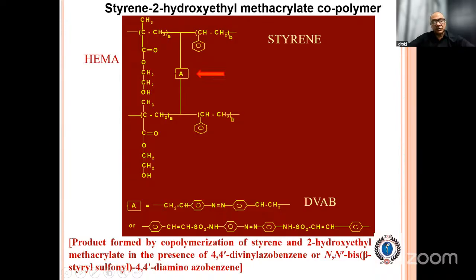So this polymer will be exclusively used for delivering drug to the colon because it is degraded only in the colon. This azo bond will be cleaved in the colon. By the cleaving of this azo bond, the polymer structure will become porous and the drug will be released. But during the synthesis of this azoaromatic copolymer, one thing we must keep in mind is that we should have a controlled degree of polymerization in the presence of the cross-linker.